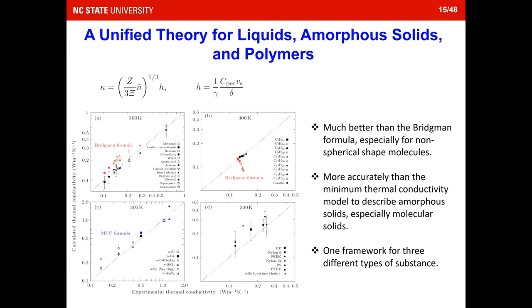On the top two figures, A and B, we're using the Bridgman formula, which has been used for so many years to describe the liquid. You can see that in the first figure, the Bridgman formula actually overestimates the thermal conductivity for all kinds of liquid. On the right-hand side, if we use different kinds of small molecules and small polymers with different lengths, you can see the Bridgman formula will underestimate thermal conductivity, especially if you have a lot of carbons in the chain. But our model actually matches pretty well.